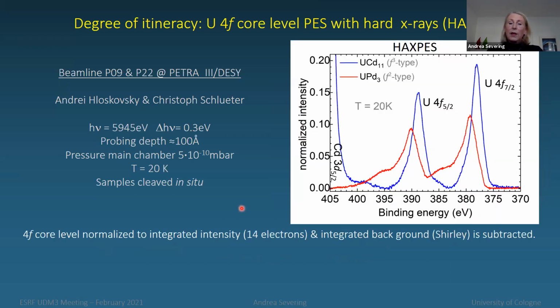That is very nice. And here is the first core level spectrum I'm showing you. I'm showing you normalized intensity against binding energy, and here in blue the uranium cadmium 11, again our f3 type uranium compound, and in red uranium palladium 3, that Roberto already mentioned is the f2, or the intermetallic uranium compound that is meant to be closest to an f2 uranium. The data have been background corrected, so we have subtracted an integrated background, and they have been normalized to the integrated intensity in the region of the 4f core level.